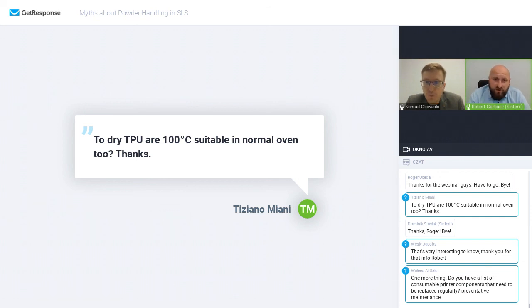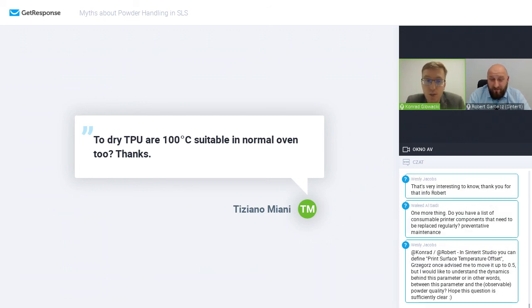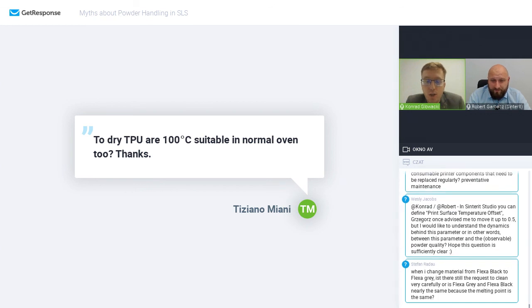thoughts or conclusions, or you think that your TPU is not like it should be, just contact us and we will tell you, and we will evaluate your TPU. But definitely TPU doesn't absorb a lot of moisture. And we will not recommend 100 degrees because the softening point for our TPUs is 60, 67, 75 degrees. The melting point, I think, is lower than that. No, melting points are above, but the softening is below 100.